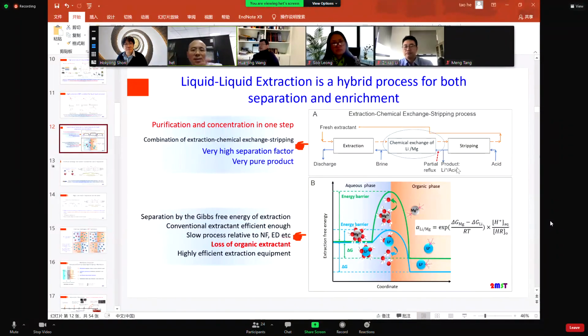This is the product, but it's a semi-product. What we do is we use evaporation to get the acid out. When we reuse the acid, we get a concentrated lithium chloride solution. In the lab, we have done this research. We reach 20% lithium chloride solution. So when we have a lithium chloride solution, we can use it directly as a raw material, or we can put some sodium carbonate to precipitate. Okay. Before evaporation, what concentration can you get? We get a 20% lithium chloride. Okay. All right. Yeah.